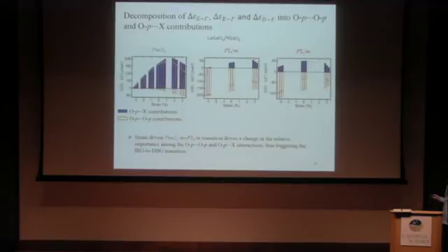And we then decompose the energy difference between the S and gamma point in the band structure of the polar phase, and also the energy difference between ED and gamma point in the band structure of the nonpolar phase, into the PP contribution and the PX contribution. Then we found the PX contribution can be positive and the PP contribution can be negative. We also found that in the polar phase the PX contribution dominates, and in the nonpolar phase the PP contribution dominates, which leads to the indirect band gap in the polar phase and the direct band gap in the nonpolar phase.